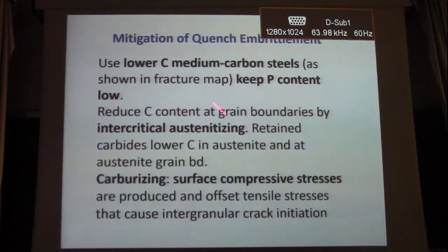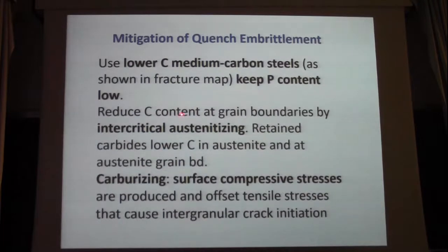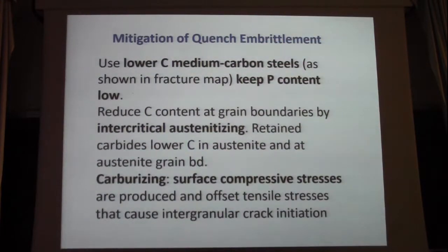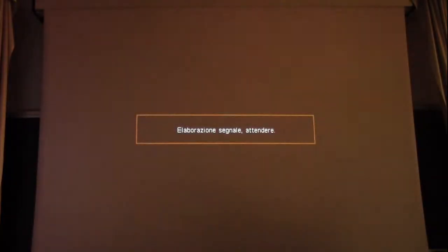Now, mitigation. Well, obviously, use lower carbon, medium carbon steels. Keep phosphorus content low. Reduce the carbon content of grain boundaries by intercritical austenitizing. Bearing steels. There's a bearing steel, 52100, 1% carbon, deep into this range. But the bearing steels, 1% carbon, these are usable. So why are they usable? Because of intercritical austenitizing. And then